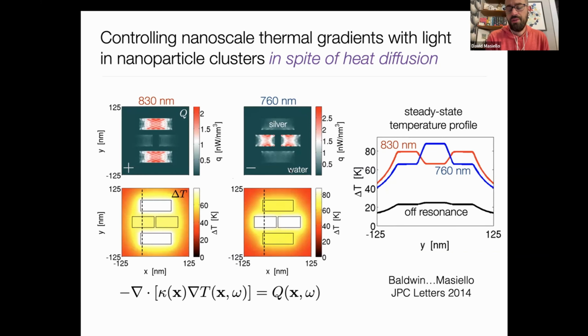And I forgot to say here, the background is water. And I'm sorry, earlier I said gold. I meant to say silver for the composition of the rods. It doesn't matter. The same thing works with gold. And really the secret of the spices here is that the thermal conductivity of water is two or three orders of magnitude below that of silver. And so what that means is the ambient thermally conductive environment serves as an insulating jacket around each one of these nanoparticles so that heat cannot efficiently outcouple and flow and equilibrate the temperature across the tetramer structure. And so here you're just seeing a couple of lineouts of the increase above room temperature of the thermal profile of these four rods driven at each wavelength.